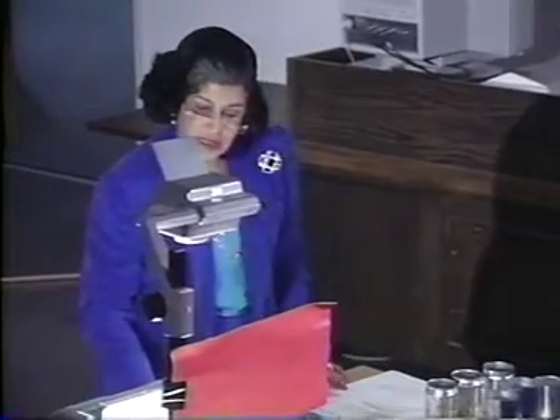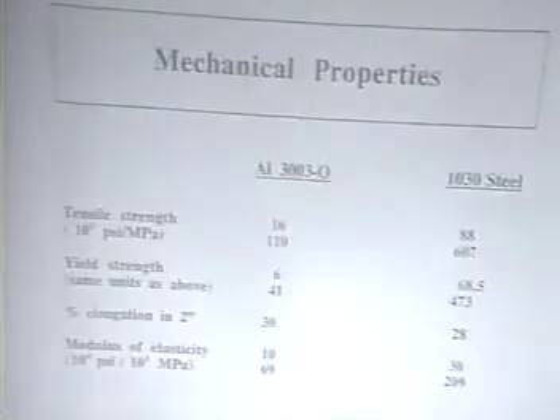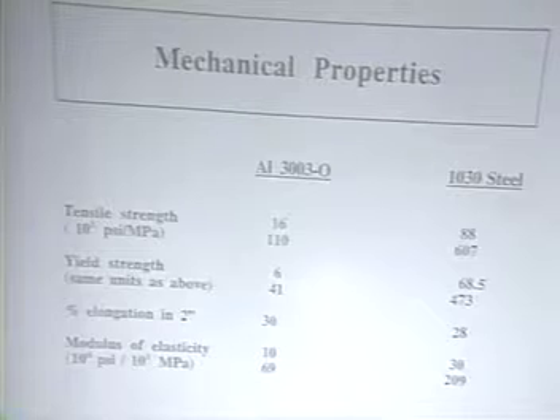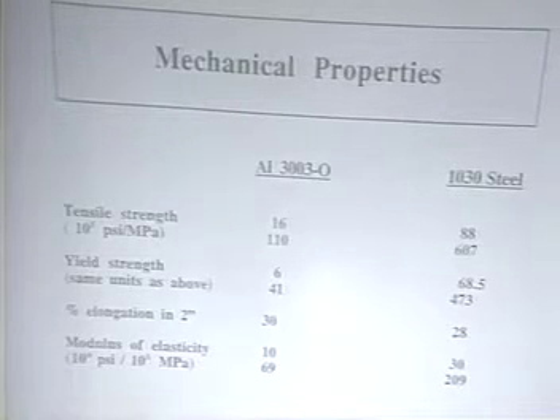If we look at alloy 3003 and compare it with, again, a low carbon steel, for 3003 with a little bit of manganese, we've got a tensile strength of 16,000 psi, a yield strength of only 6, a percent elongation in the gauge length of the tensile specimen is 2 inches of 30, and a modulus of elasticity of 10. And you can see how it compares. The only place that it's close is with percent elongation with the steel, with the low carbon steel.